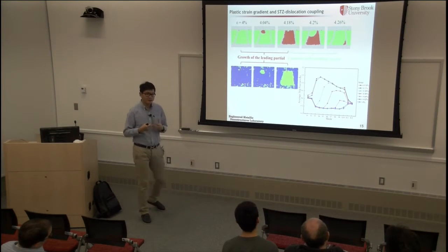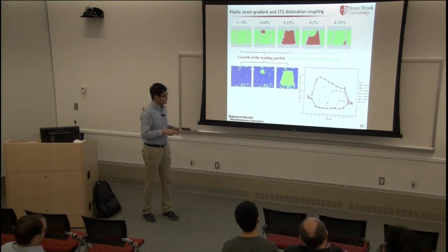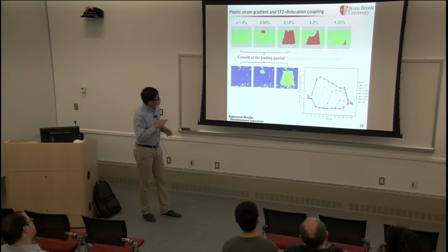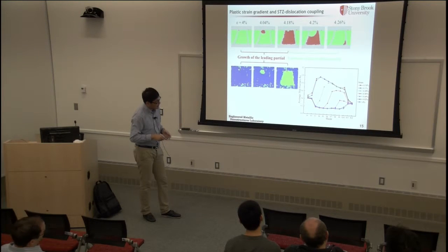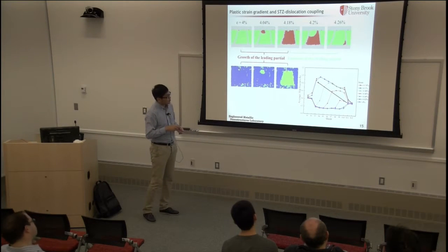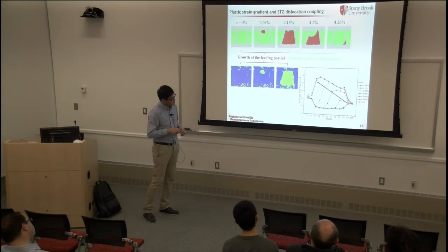And we applied a similar slice analysis to this study, and we found that when the leading partial is emitted, we already see the strain gradients at the upper interface slices S10, S11. And with the dislocation emission, the crystalline layer slices have been progressively elevated. And when it's absorbed by the lower amorphous-crystalline interface, the amorphous interfacial slices have been enhanced.